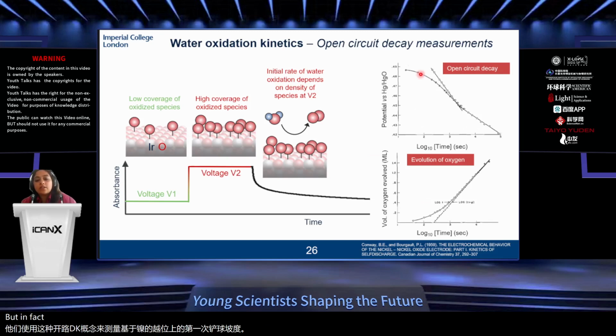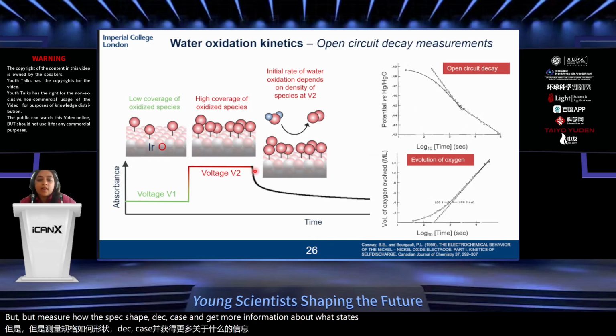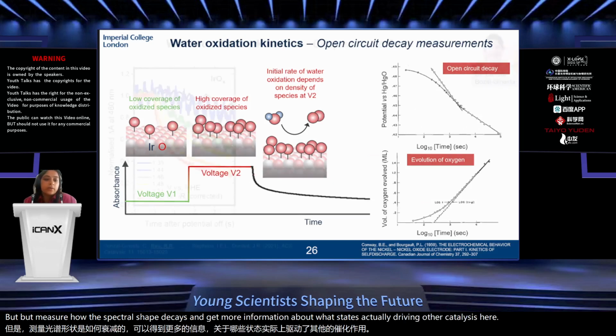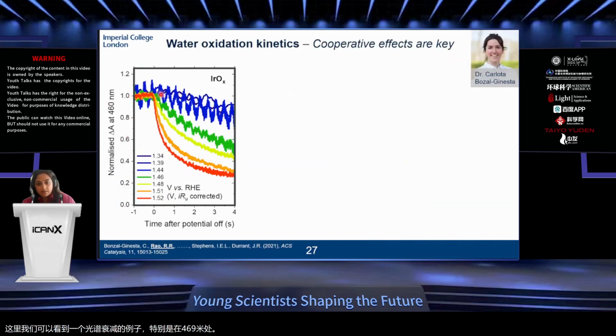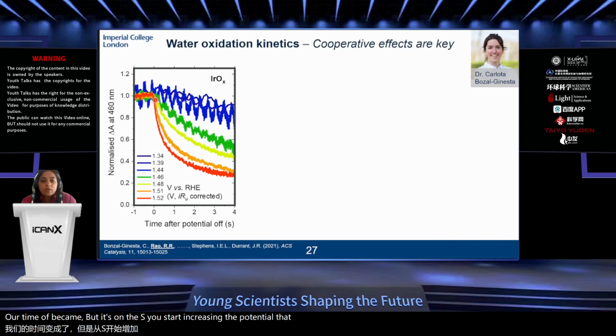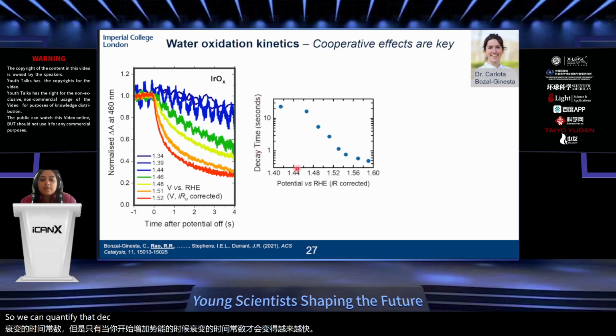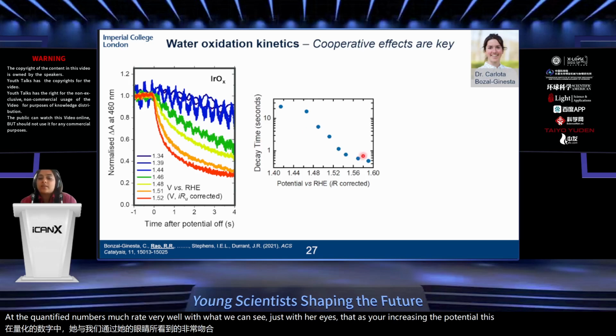But the additional bit of information that we can get now is not just measuring how the potential decays, but how the spectral shape decays, and get more information about what states are actually driving the catalysis here. So here we can see an example of the spectral decay, specifically at 460 nanometers. And from this data, we can see quite nicely that at low potentials, you have this really long time constant of decay, but it's only as you start increasing the potential that this time constant for decay starts getting faster and faster. So we can quantify that decay time as a function of potential, and the quantified numbers match very, very well with what we can see just with our eyes, that as you're increasing the potential, this decay time is getting faster.